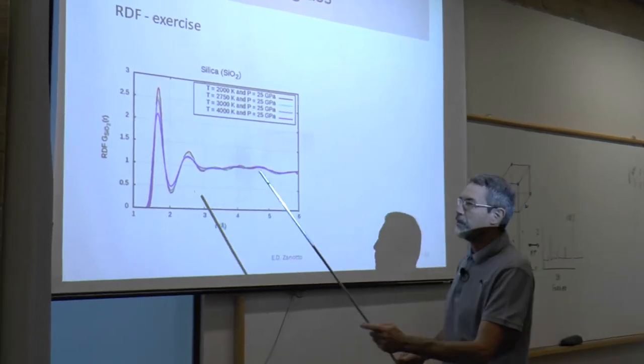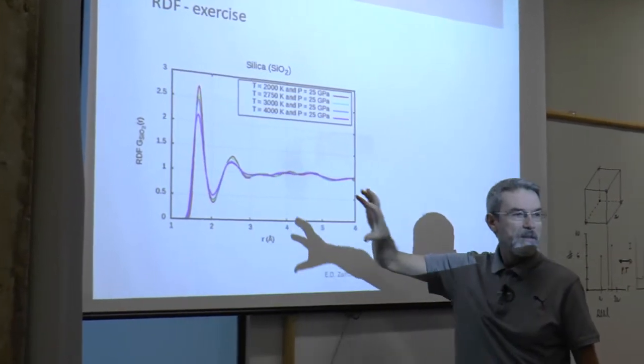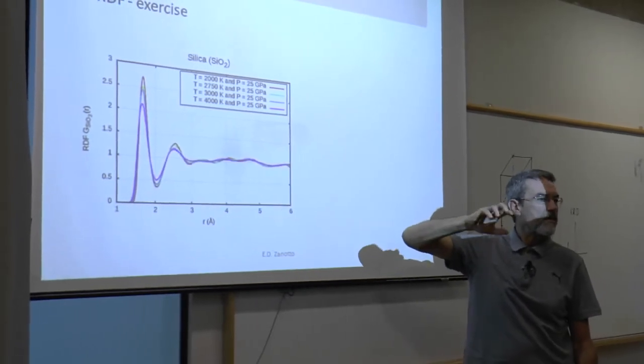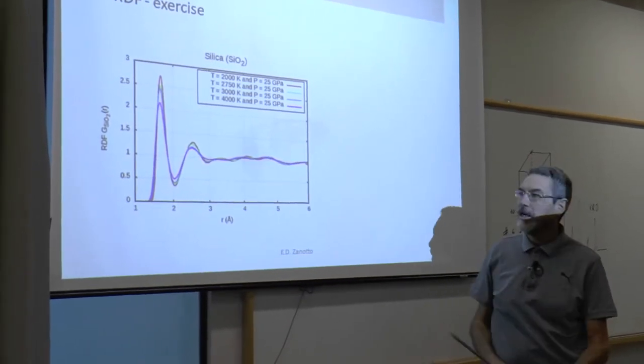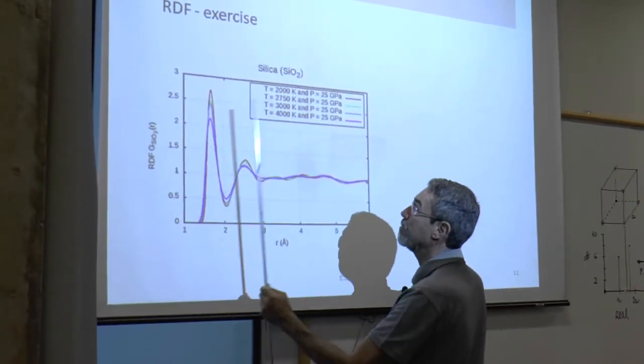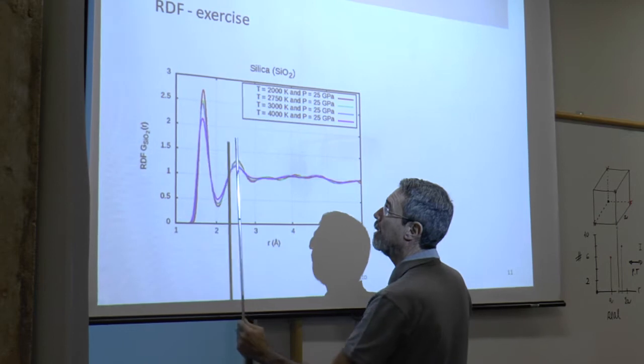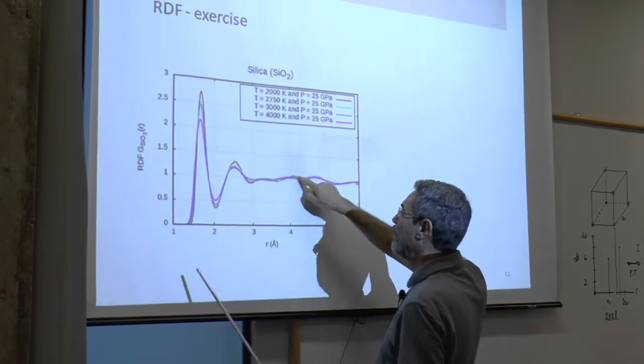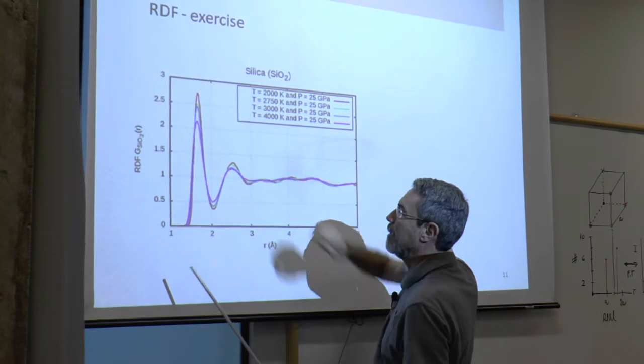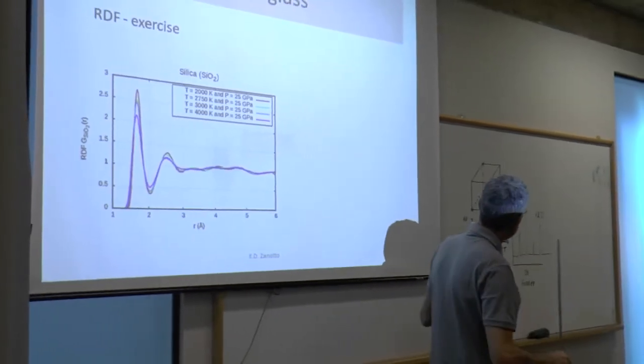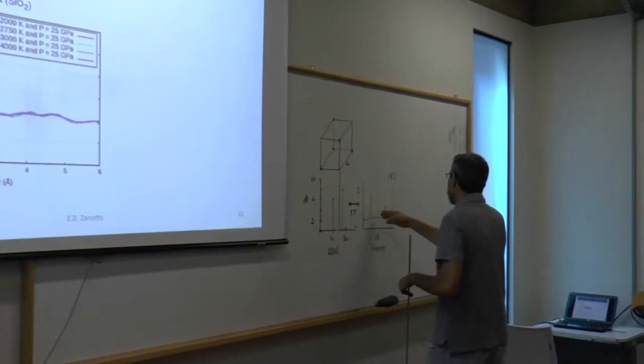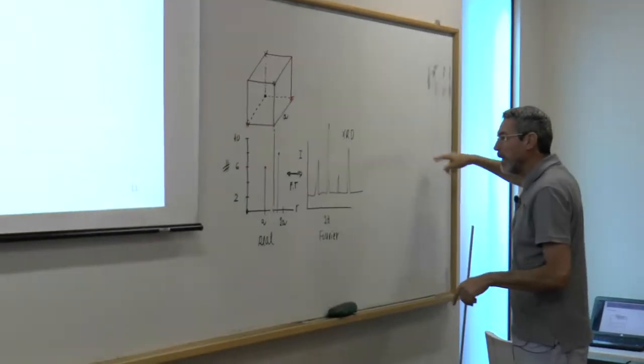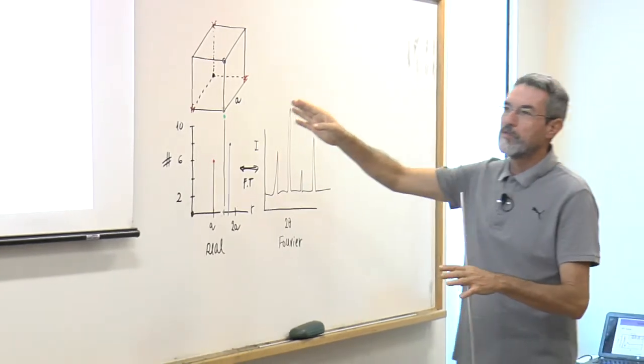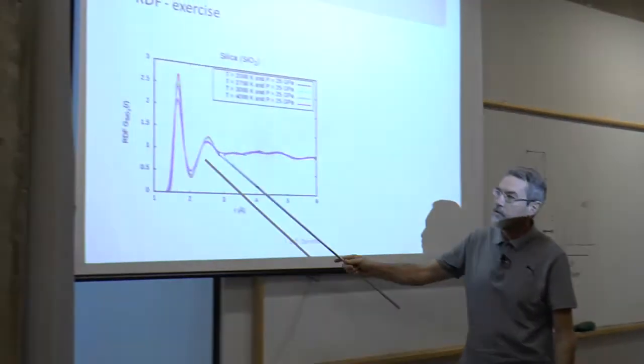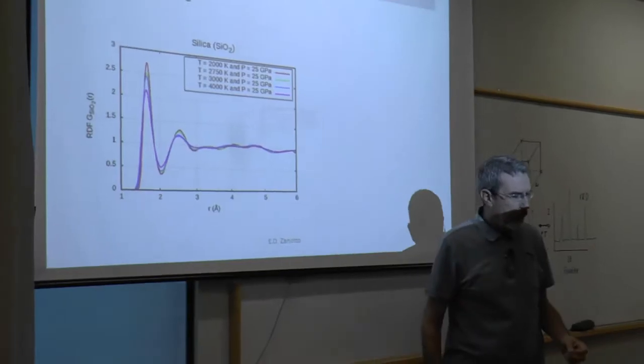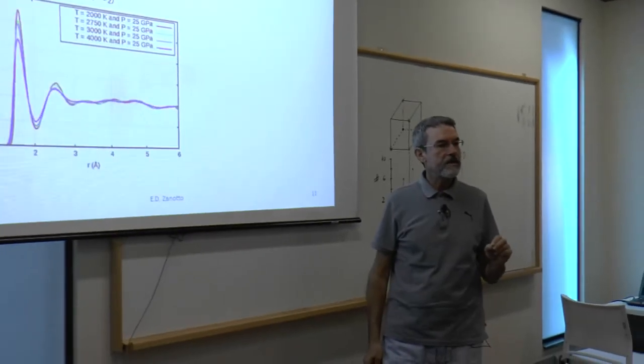But the nice feature is that even the X-ray diffraction of a glassy material has at least two peaks, in this case of silica glass. It's a very nice peak here, a very nice peak here, and then it has a very wide peak here. In these two peaks, it's not like a crystal which had many peaks because of the ordered structure, but this shows that the structure of glasses is ordered at very short distances.